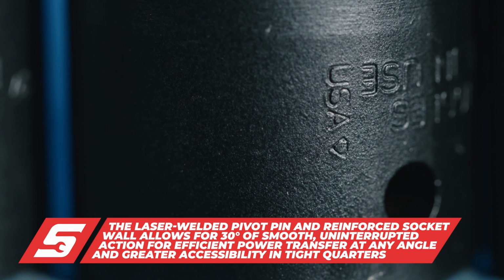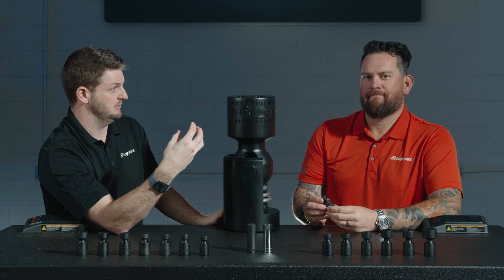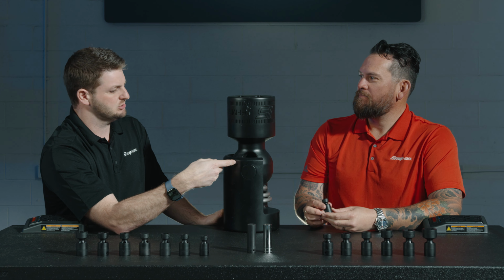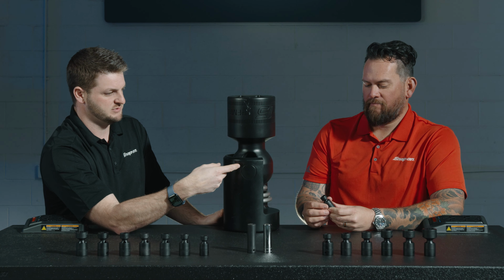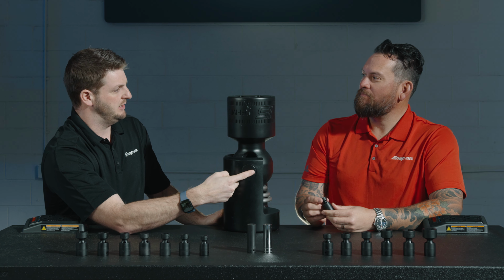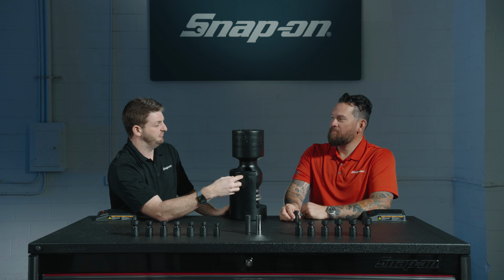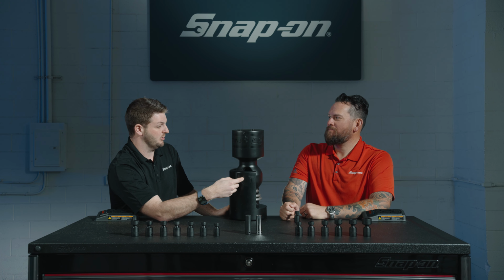Because as we talk about heat treat, we've talked about this with punches and chisels, right? When you need to sharpen a chisel, you do that by hand. You don't want to use a grinder because you're introducing heat and you're changing the heat treatment that's applied. The same is true with an impact socket or a chrome socket. You want to reduce the amount of heat so that you don't have a failure here at the point where you're permanently joining this.